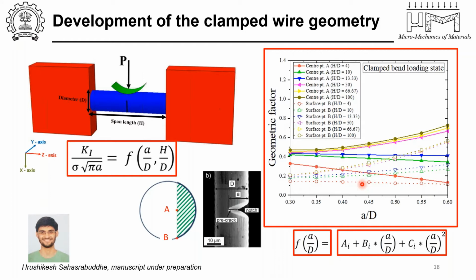The other point that was of importance was the wire length, again, the aspect ratio of the wire. Here we talk about the aspect ratio as the height versus the diameter. So that aspect ratio is also a variable. Let's say I pick up a fiber and each of the fibers has a different length. It's very hard to cut that particular fiber. So I make a notch and I test them under bending. Then I should be able to extract the fracture toughness of that particular fiber. And then I can incorporate that in certain micromechanical models where I look at composites and so on.